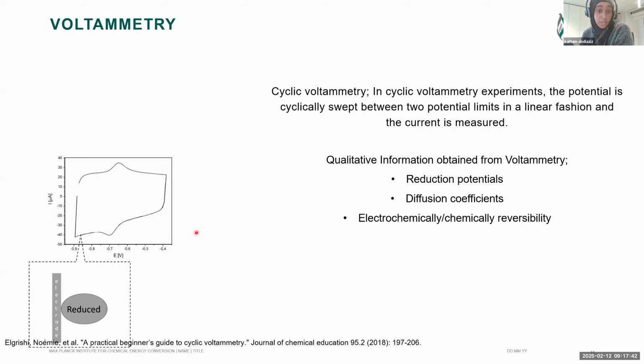And some of the information that you can get from voltammetry includes reduction potential. So this peak here is the oxidation peak, and this one's the reduction peak. And the potential between these two peaks gives the reduction potential. You can investigate diffusion in your system by looking at the dependence on your scan rate, which is how fast you scan between your two limits. And then you also get information about your redox reaction, whether it's electrochemically or chemically reversible.